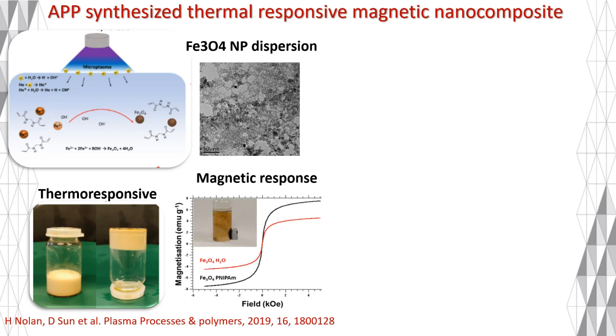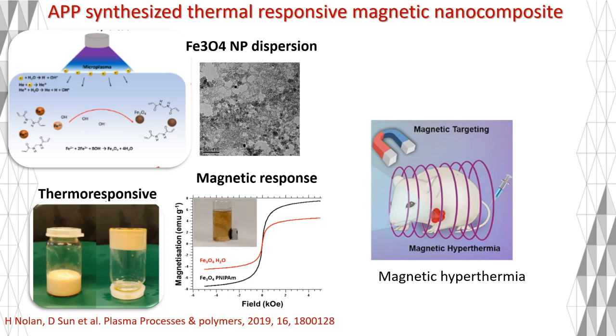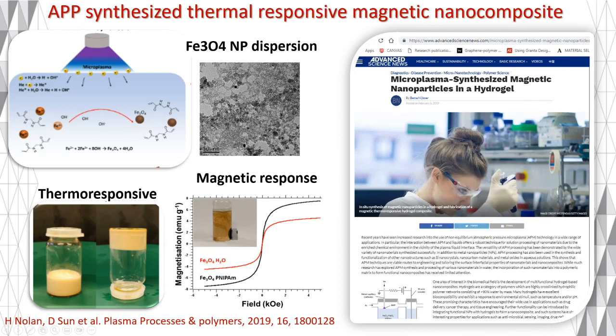So how does this magnetic hyperthermia work is that at room temperature, the composite is in the liquid state, and that allows for its easy injection into the tumorous site. And once exposed to the body temperature of 37, the composite will undergo a phase transition from liquid to semi-solid gel, and hence immobilizing the magnetic particles at the tumorous site. And by applying an external AC magnetic field, the magnetic particles will generate heat, which can be used to ablate or kill the cancer cells. And it's with pleasure that this piece of work has been featured by Advanced Science News website, underscoring its research potential and significance in the field.